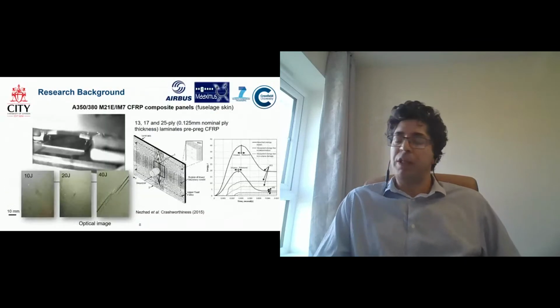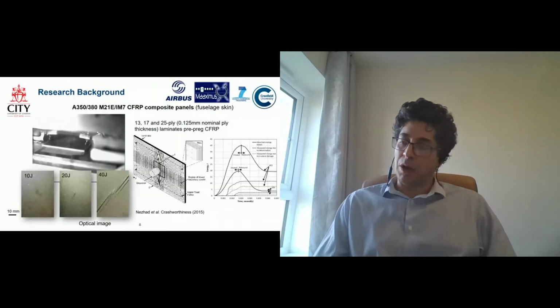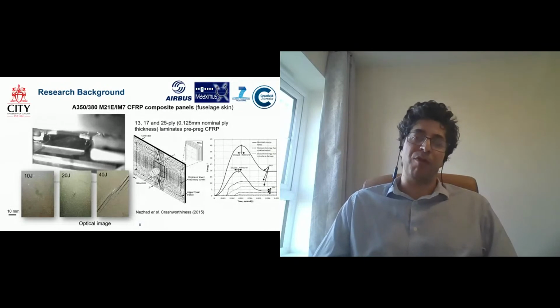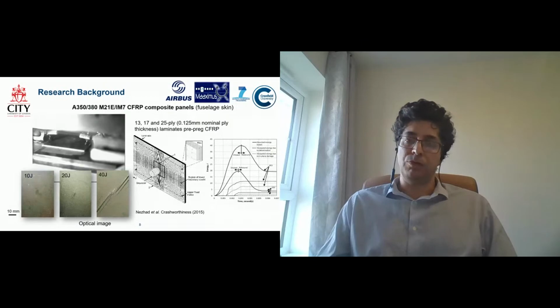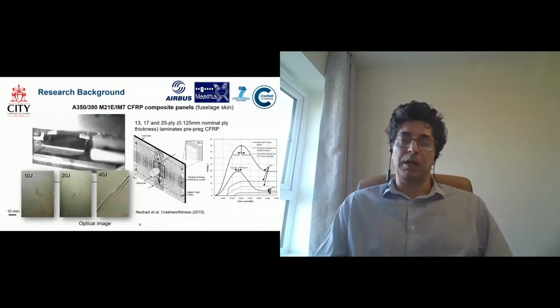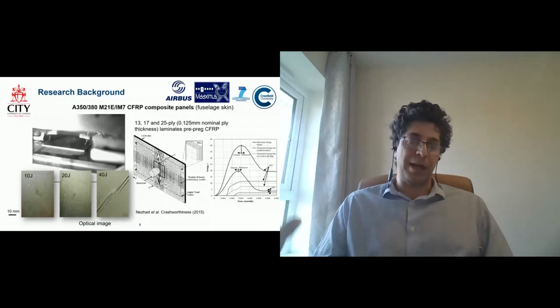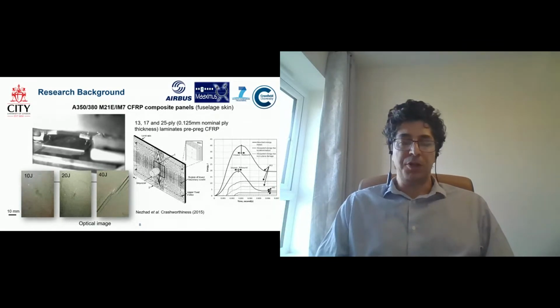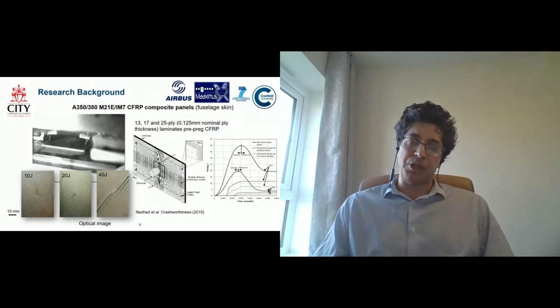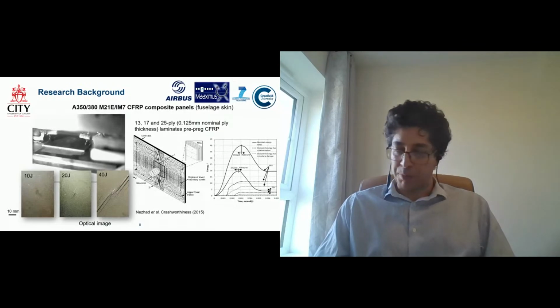Just imagine that we don't need to get catastrophic damage caused by flutter, for example, or ground vehicle substantial damage or bird strikes. We can have slight damage of a tip or tapping of the specimens, like this experimentation. You see the video here on the low velocity impact that will cause up to about 100 joules of energy only. So you don't see that much damage on the surface of the very high performance structure.